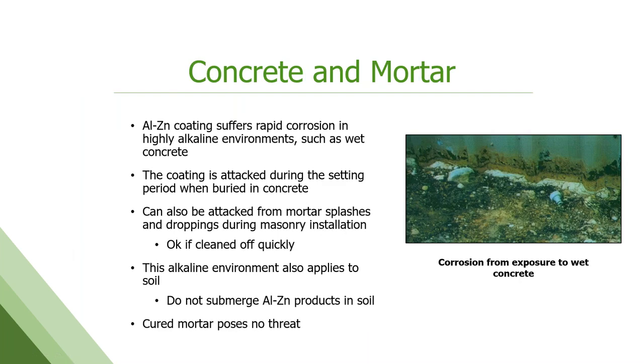Concrete and mortar is problematic for Galvalume too. So it really suffers quickly from wet concrete. And this is an example of where they poured a concrete slab right up against some panels without a flashing in between, and it just eats away at the panel very, very quickly. Mortar splashes on a job site can be problematic too. They need to be cleaned off quickly. If they're allowed to sit for a period of time, they will start eating through the coating as well. And again, don't submerge the Galvalume product in soil.